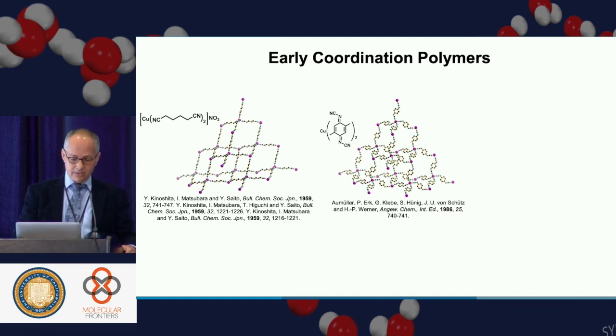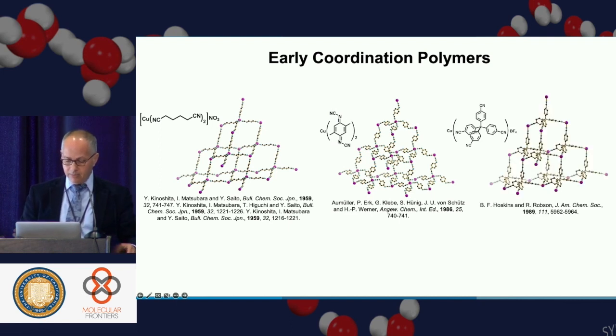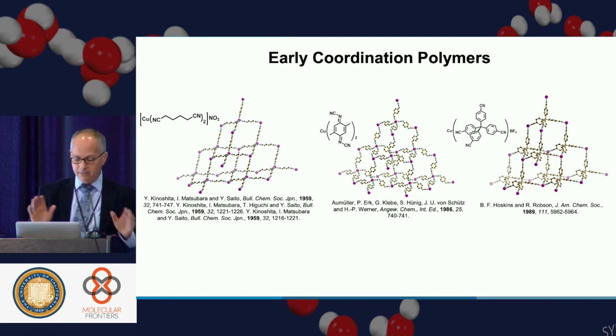And the same thing was illustrated also in 1986 for the same kind of network, but now this diimine dinitrile, same chemistry, and the same thing was also repeated in 1989, but now with a tetranitrile, okay? And all of these are based on diamond structures. They're all based on copper-1 linking nitrile neutral linkers. And they all have this openness into which ions can balance the charge. And since that time, or around that time, there have been hundreds of these made.